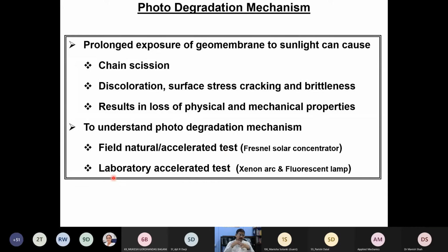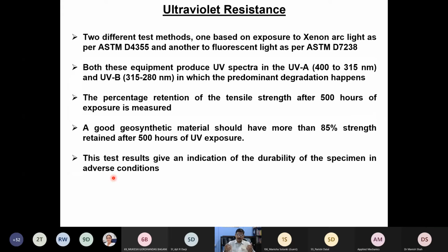As a result, we may have to resort to laboratory accelerated tests, where you subject the polymer to a higher level of radiation. We use either xenon arc weatherometers or fluorescent lamps, because of the significant portion of sunlight, only the UV region is going to cause degradation. So we use fluorescent lamps which emit only UV radiation, and we can really assess the photodegradation. So this is some of the ways people are doing it in the laboratory, and you need not really worry about the testing methodology.